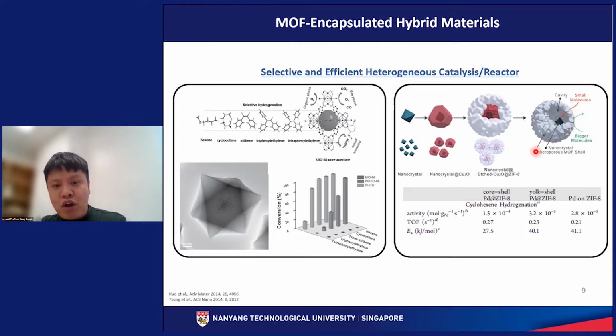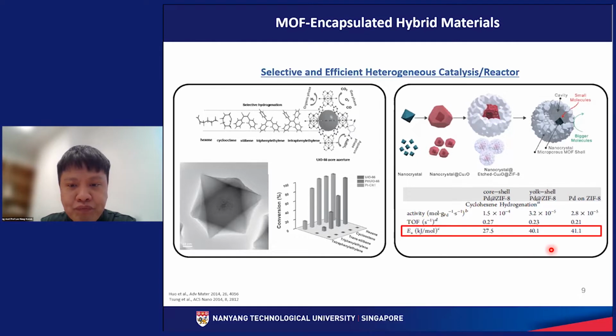But what is more important is highlighted over here. From this table, we can see that the activation energy, which is the Ea over here, is much smaller in a core shell structure compared to yolk shell, or simply palladium deposited on ZIF-8 MOF. By having a lower activation energy, my reaction kinetics will be faster, right? This is something we want to achieve in our catalytic system. We want to reduce activation energy.